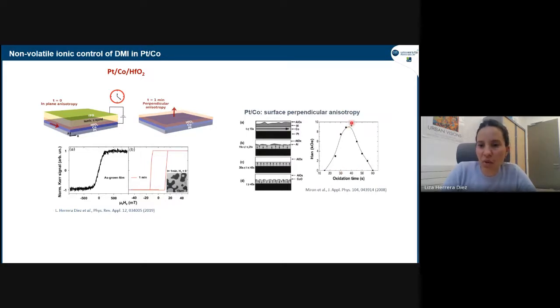But then there's a window of oxidation where the system favors perpendicular anisotropy. And this is what we linked to our system. We said, well, it's a system that comes out of the deposition chamber. It is under-oxidized. We pump some oxygen inside because we apply a negative voltage, which was compatible with oxygen species moving towards the magnetic film, and then we recover PMA.